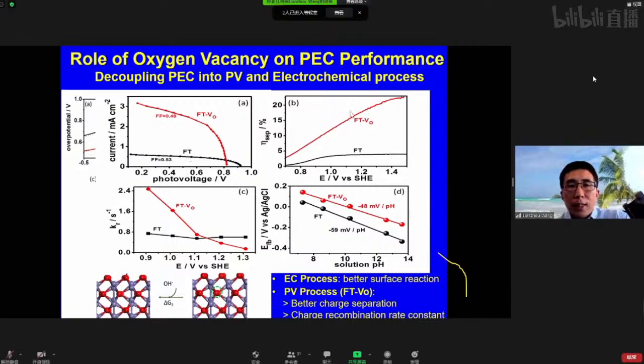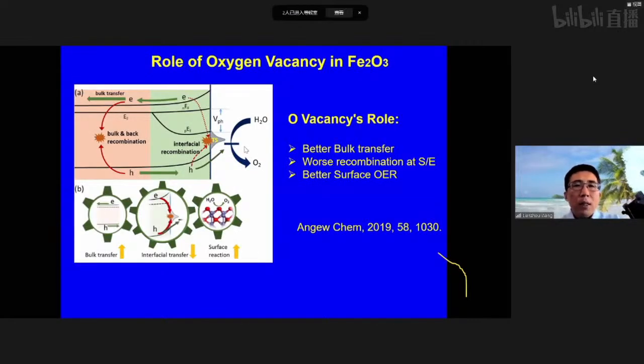And we also look at some other performance, like charge separation difference, and we found there's quite some difference between these two electrodes. And what does this mean? This means, in the whole process, if this is the photoelectrode, in the bulk, after we introduce the oxygen vacancy, the charge carriers are able to transfer more efficiently.